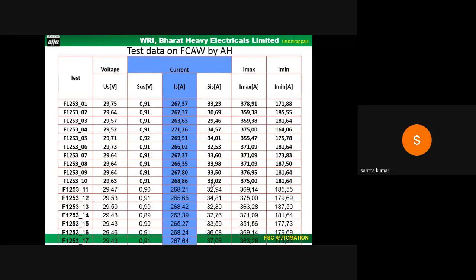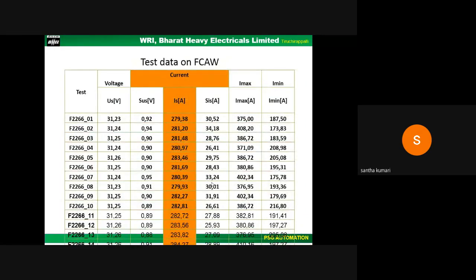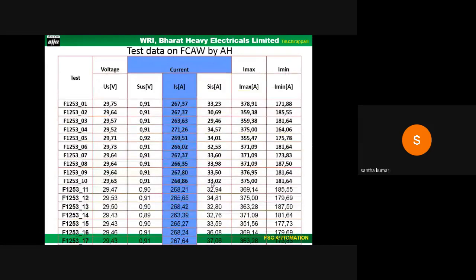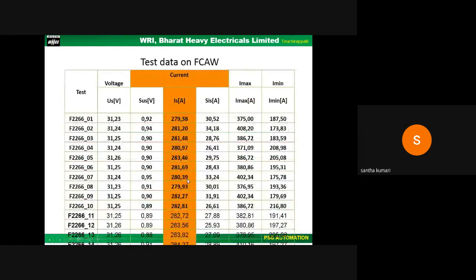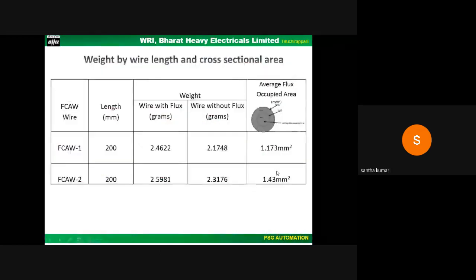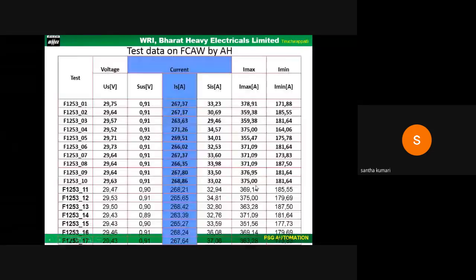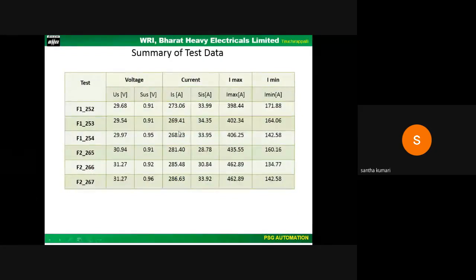On analysis, it was found that the flux filled area differed. For this study, fully mechanized welding trials were carried out with a robo controller in 1G position on 20 mm thick plates of common low carbon steel, using a power source operating in constant voltage mode with continuous monitoring of the welding current and voltage. There are significant differences in the statistical values of the mean value of the welding voltage on the arc. You can see here the current of the first set of wire and the current of the second set of wire had increased. This way also we can see that, as I said, the second set of wire had an increased average flux occupied area. So this could be evaluated using a digital data acquisition system.